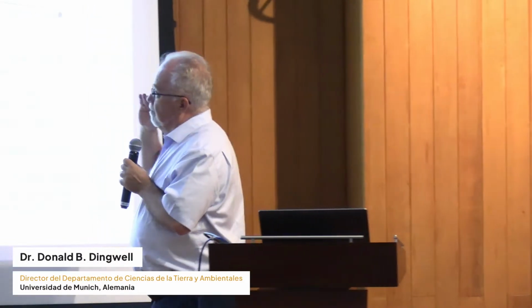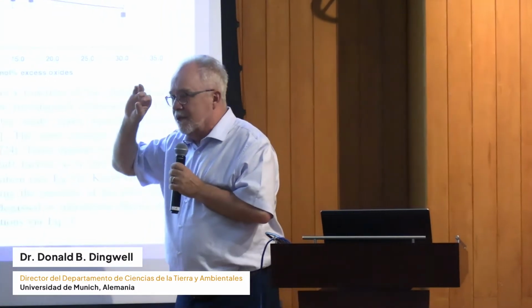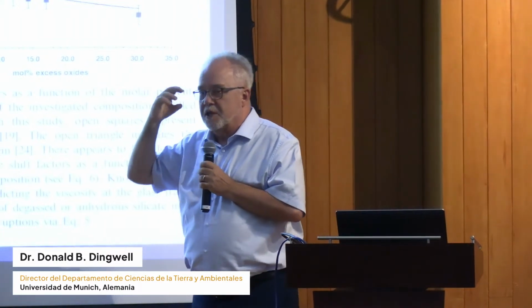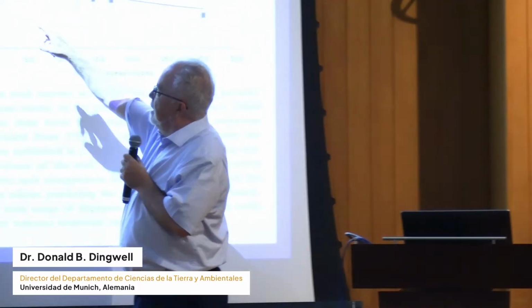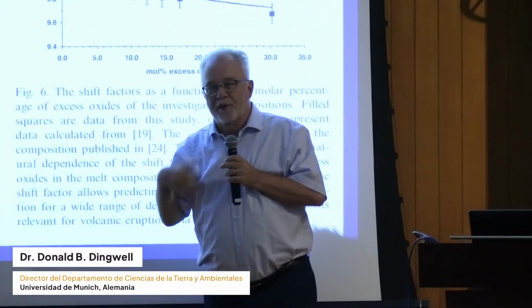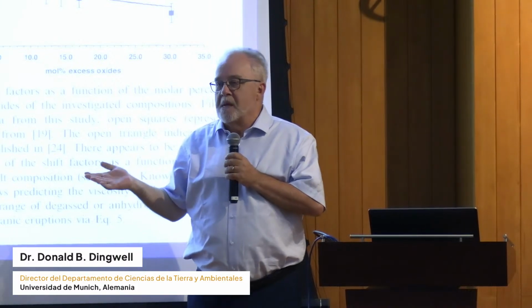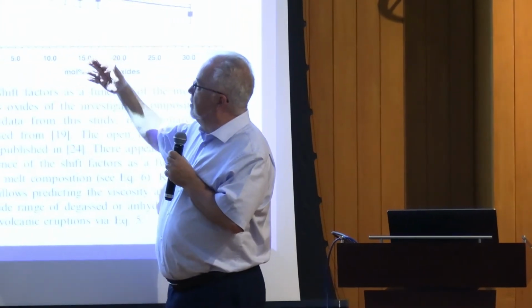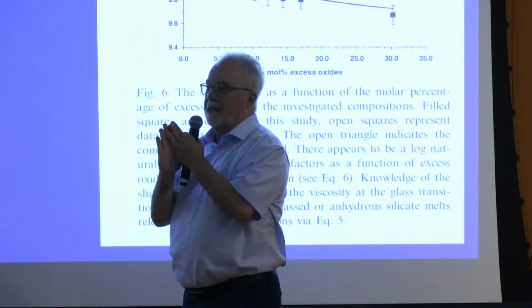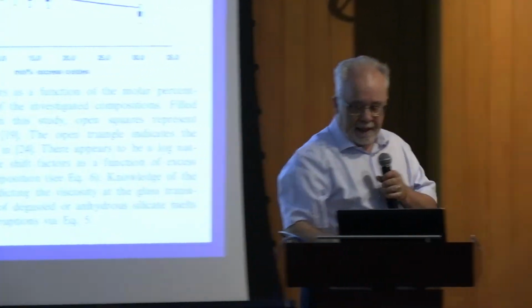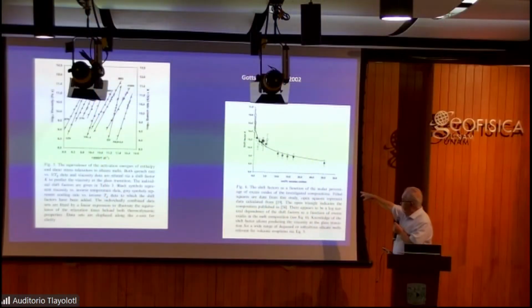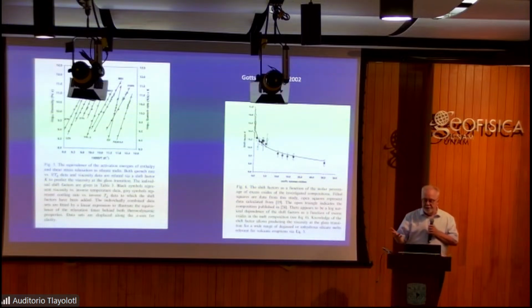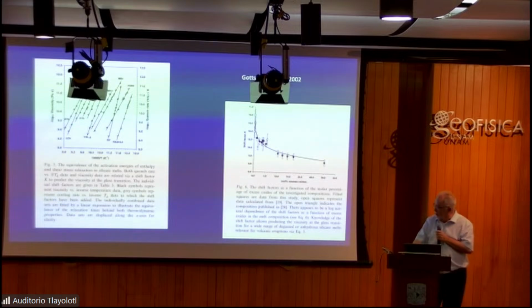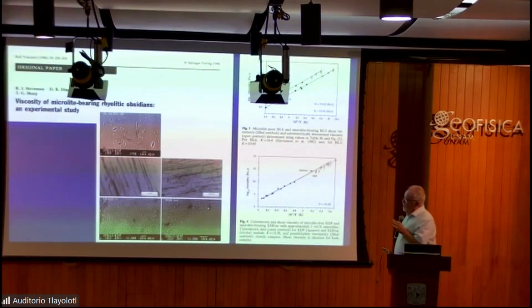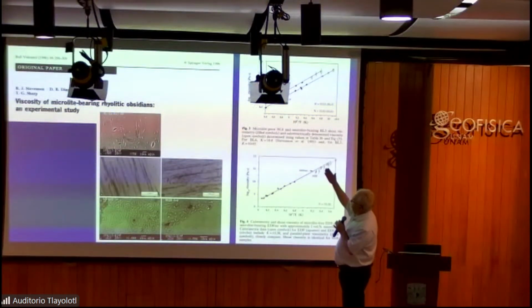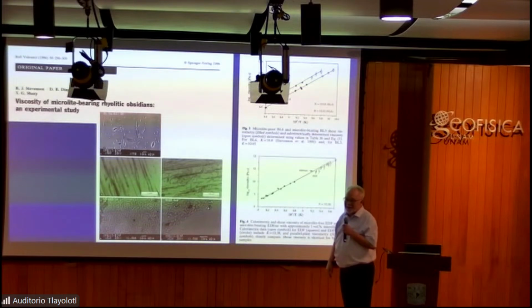So it's not perfectly independent of composition. There's another level, a subtle added level of variability which depends upon composition. That's taken up in what we call the shift factor. We didn't call it that, we took it from the literature. It had already been worked out for glasses in synthetic systems. The shift factor literally means how much do I have to shift one of these curves to make it superimposed on the other. But when you can calculate the shift factor as a function of a compositional parameter, it allows you to predict the viscosity from a calorimetry trace or a calorimetric peak from a viscosity determination. So we used this, again, back in the 90s. That was my annus mirabilis, 1996, when everything suddenly makes sense.